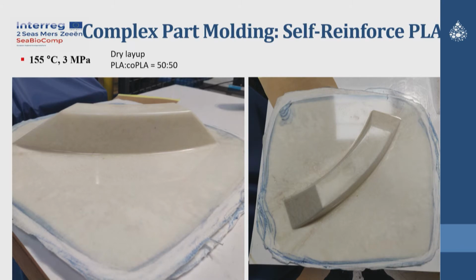And the question of manufacturing feasibility, especially complex part molding. In general, the big challenge of compression molding is to manufacture parts with a deep draft angle and a corner, where we can frequently observe wrinkles and low pressure application. So this is the result of compression molding using the self-reinforced PLA nonwoven prepared by the dry-laid process. You can see that there is no dry zone, no visible void, and no wrinkle. So manufacturing was quite simple.